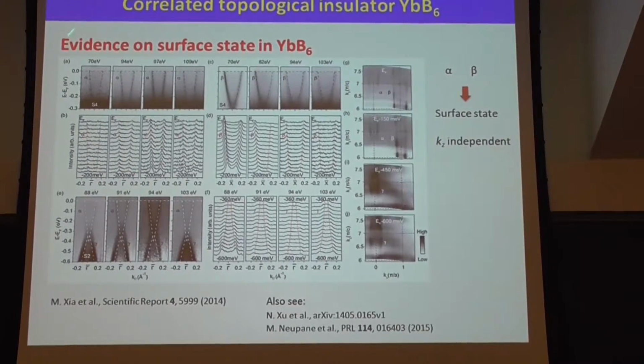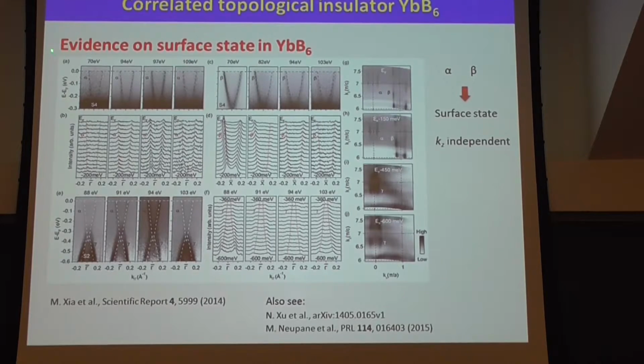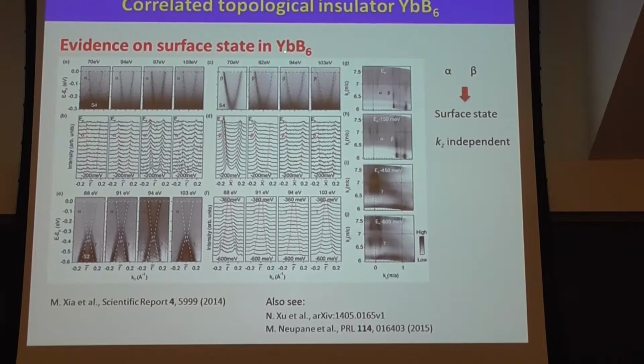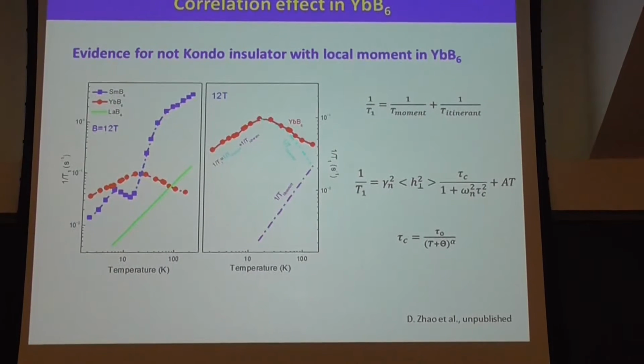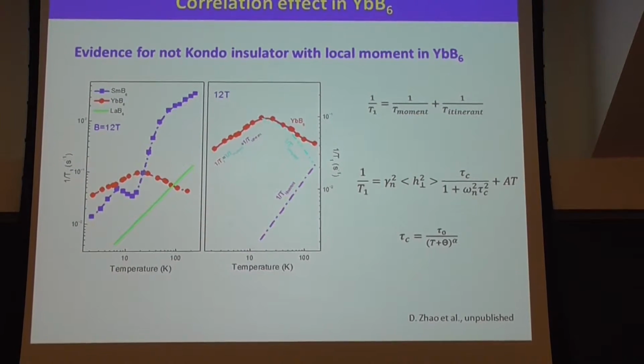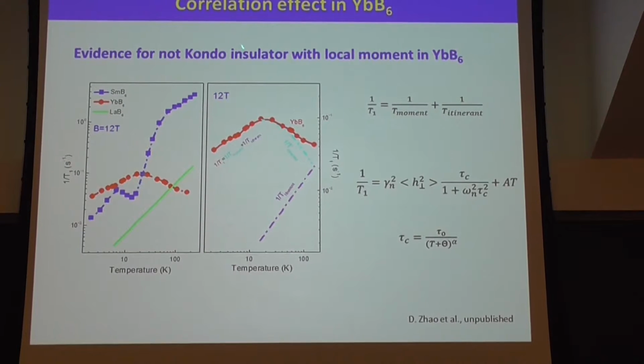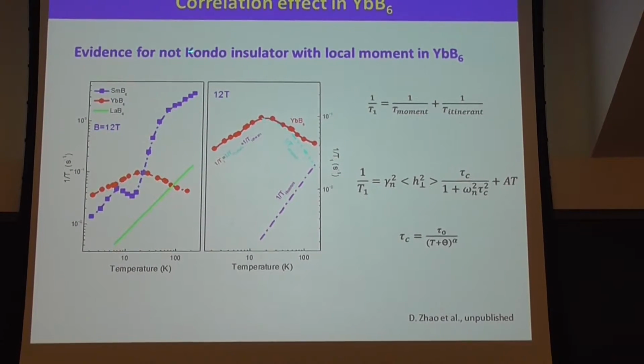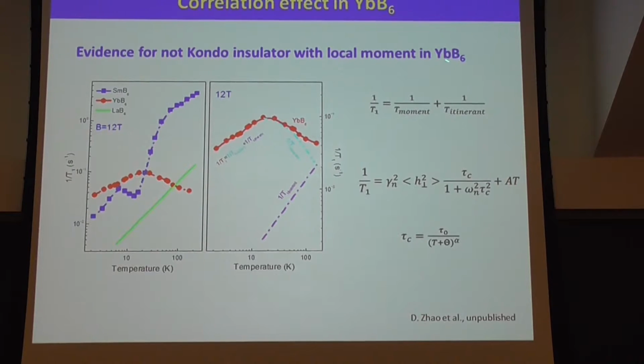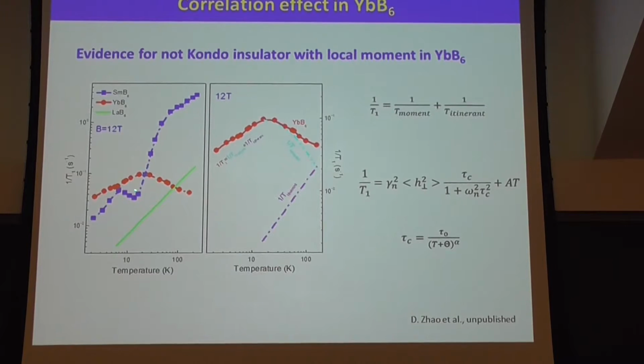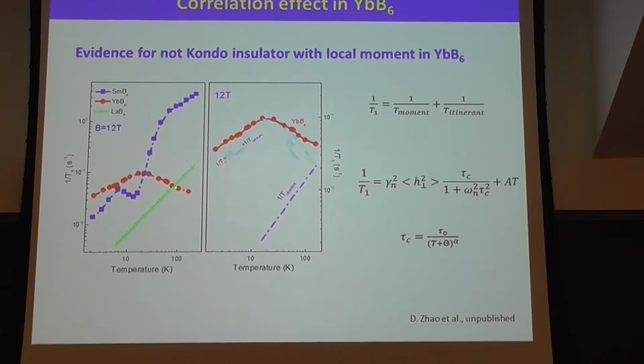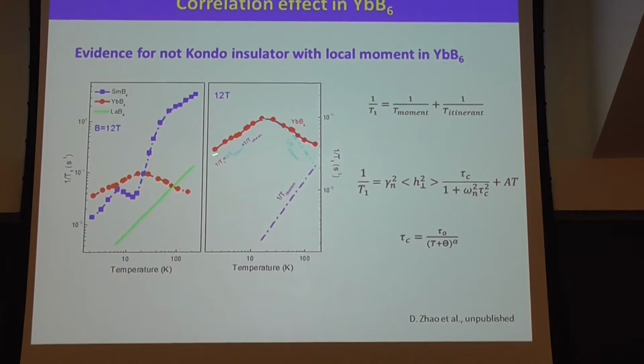And also, ARPES data shows evidence for surface states in this YbB6, because it is independent of kz, so it looks like the surface state is two-dimensional. And for this material, there is also evidence for a non-Kondo insulator with local moment. In this one, this is the measurement for the NMR data. This is for SmB6, this is YbB6, and this is for LaB6, because LaB6 is just a Fermi metal.